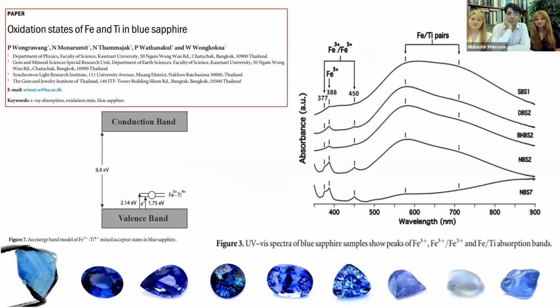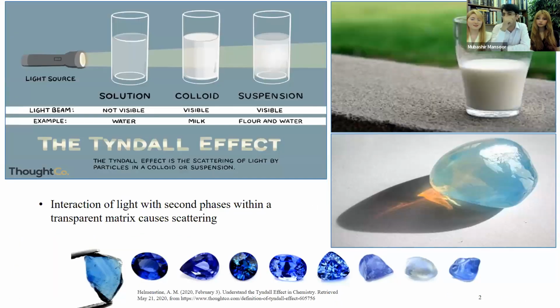Yeah, there was this other study published actually quite recently, which still does not challenge the presence of iron and titanium, but it challenges the charge states. And this study, it was a beautiful study, very detailed experimental study. They actually show that it could be iron 3+ and titanium 4+ that creates the kind of energies necessary for that hump that we observe. So, it could be that both are actually playing a role here, both iron 3+, titanium 4+, and also iron 2+ and titanium 4+. And this hump could be a contribution of all those different charges in the iron and titanium solid solution. We'll come to there as well.